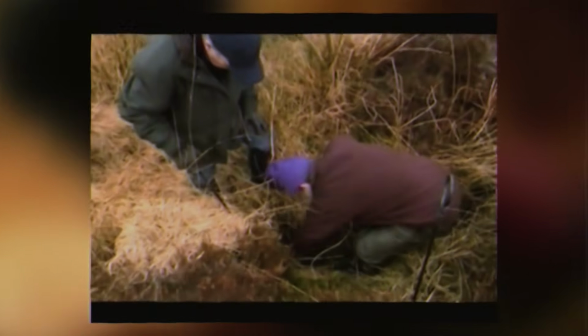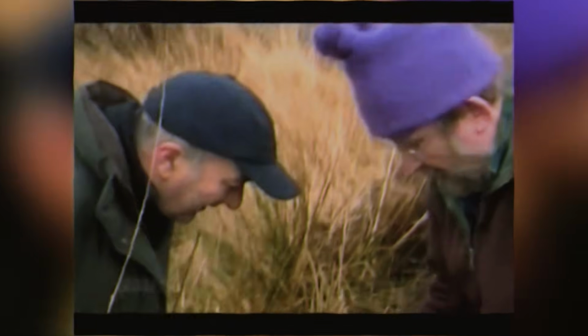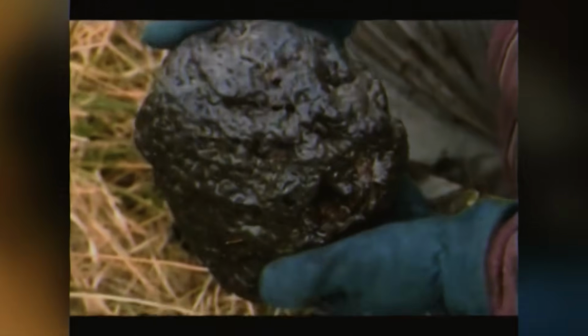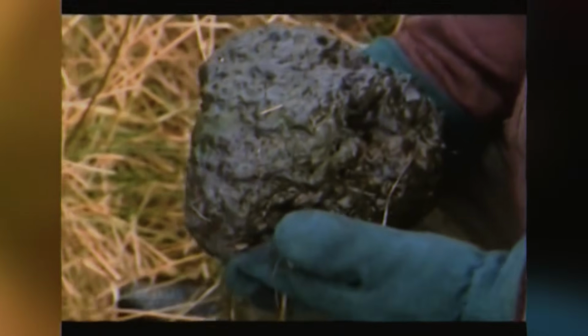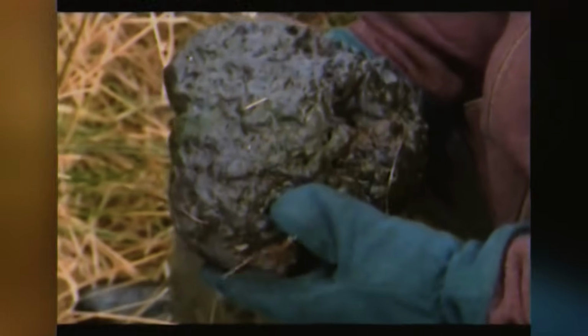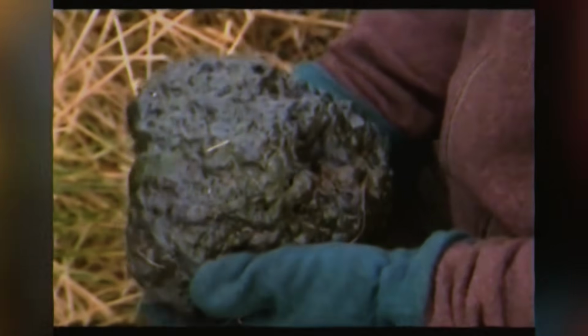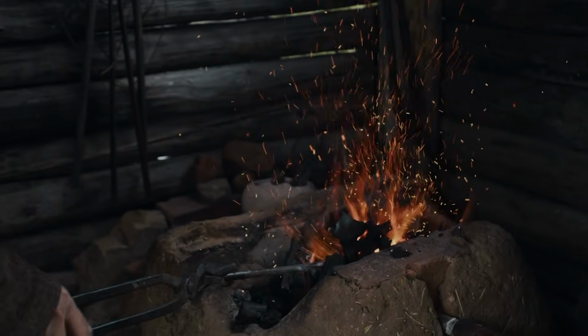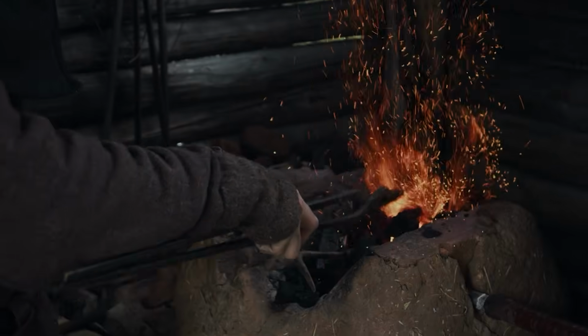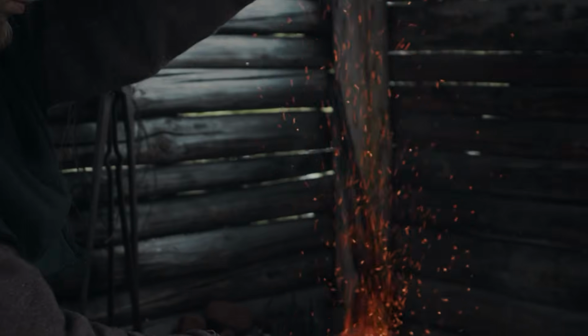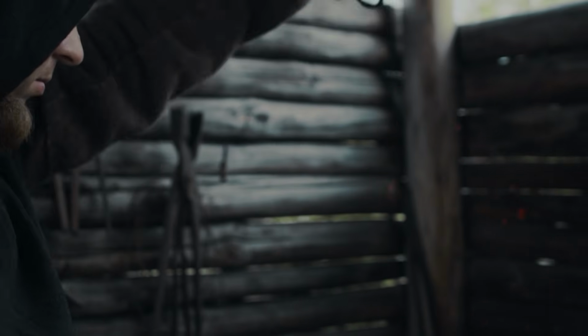When bog iron was smelted, that phosphorus stayed in the metal, and when that phosphorus-rich iron slowly corroded over decades, something remarkable happened. The phosphorus helped form a dense, stable film of protective oxides on the surface. This film sealed the metal from moisture and oxygen, dramatically slowing further rust. This was a happy accident, a beneficial impurity in the ore. The smiths did not know why bog iron worked better, they just knew it did.